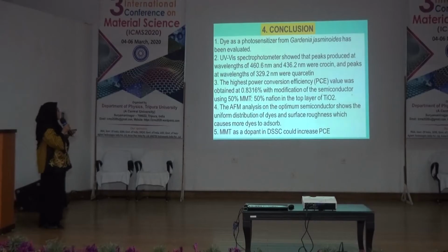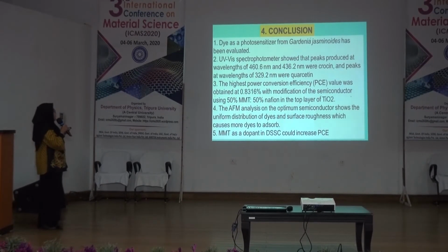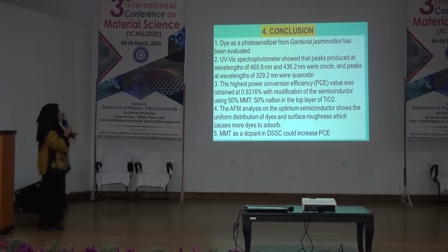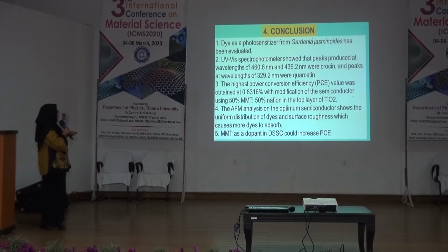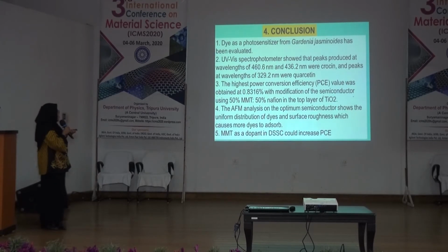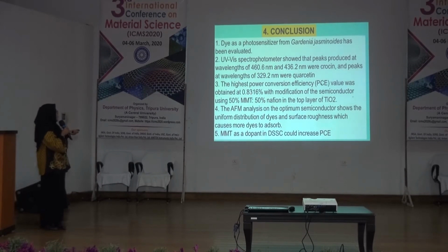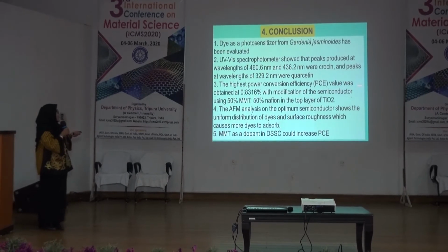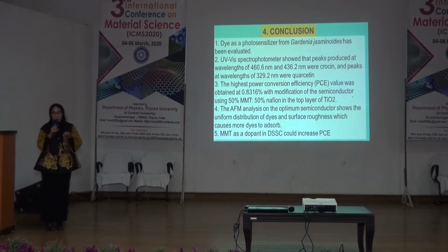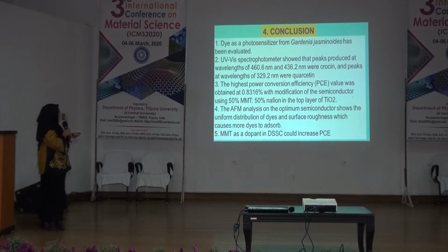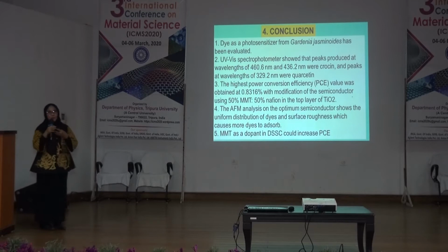The first one: dye from gardenia has been evaluated as a potential sensitizer. The second: UV-Vis spectrophotometry shows peaks at wavelengths 460.6 and 436.2 nanometers, which indicate crocin, and peaks at wavelength 329.2 nanometers with quercetin. And then the highest power conversion efficiency value obtained is 0.8316%, with modification of the semiconductor using 50% montmorillonite and 50% nafion. From the AFM analysis, the optimal semiconductor showed a uniform distribution of dye on the rough surface, which causes more dye to be absorbed.